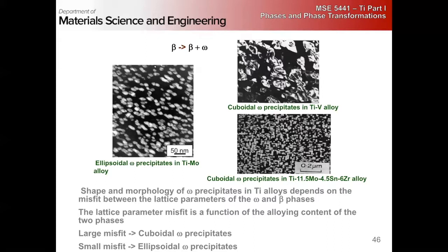if these were isotropic, except we're dealing in a crystal. So different planes will have different energies on different interfaces. By making your low energy interfaces, we'll talk about what those are in nickel, you can reduce your energy by going cuboidal.